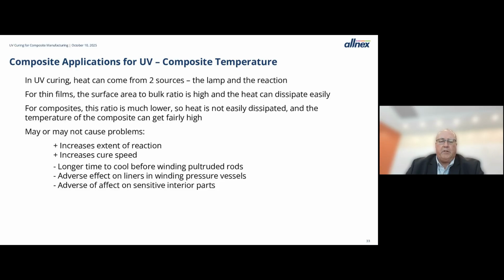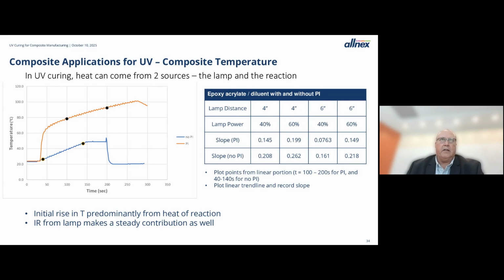Depending on your line configuration, higher temperatures mean longer cool down times before you're going to wind, say, pultruded rods up in a coil. Could have an adverse effect if you're doing a pressure vessel or some other winding application where you have a heat-sensitive liner, or sometimes you are winding composites around a material that has temperature-sensitive interior parts, in which case you have to control that peak temperature of the composite during cure. And again, these are things that you need to consider, not necessarily things that stop you from doing what you want to do.